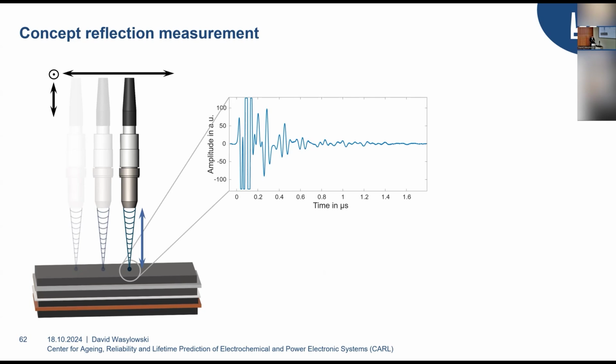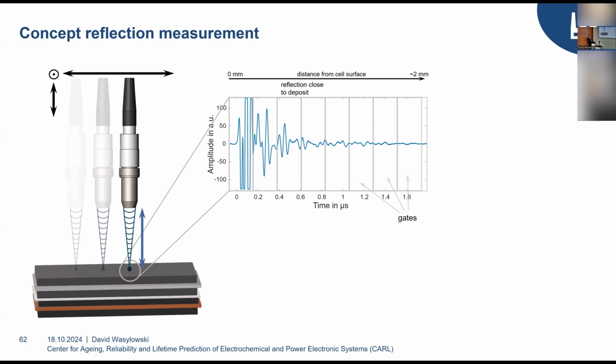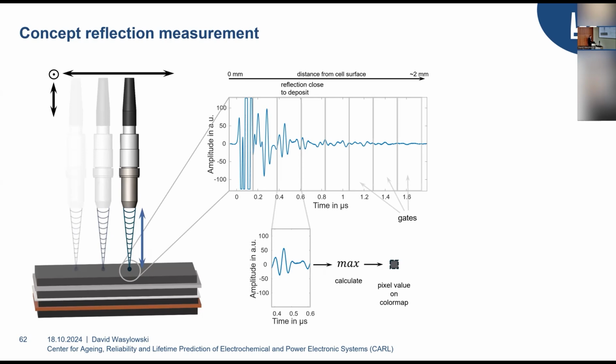And if we now analyze this reflected signal, we see all of these individual reflections, which we assume are coming from individual material interfaces within the battery. So if we translate this time domain to the depth domain using the speed of sound, we can divide the signal into gates, and each one of these gates is supposed to visualize one of these deposits. And if we only analyze now this part, which is interesting to us, so for example, the deposits we saw earlier, and assign a color map to only this one gate that is interesting to us, we should in theory be able to visualize what we want.